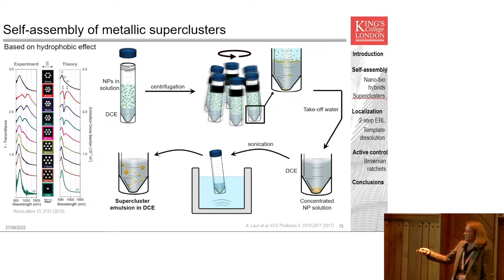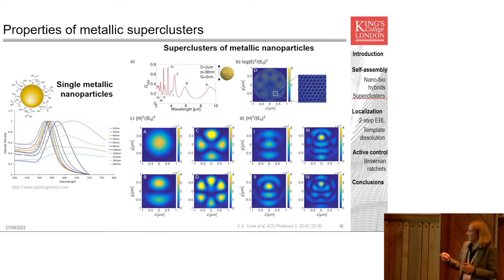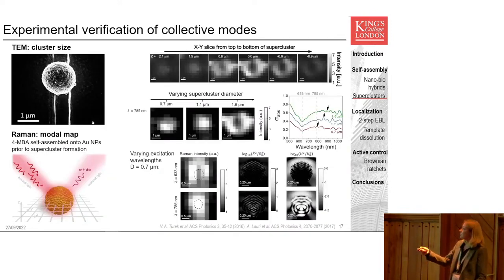We started with nanoparticles in aqueous solution as they are produced, and we add a dichloroethane, which is an organic phase at the bottom of the centrifuge tube. We centrifuge everything, which pulls the nanoparticles to the bottom of the centrifuge tube and concentrates them. We then remove the aqueous phase from the top and emulsify the solution, which creates these pockets of aqueous phase containing many, many nanoparticles. And when we dry them, we end up with these massive clusters of metallic nanoparticles.